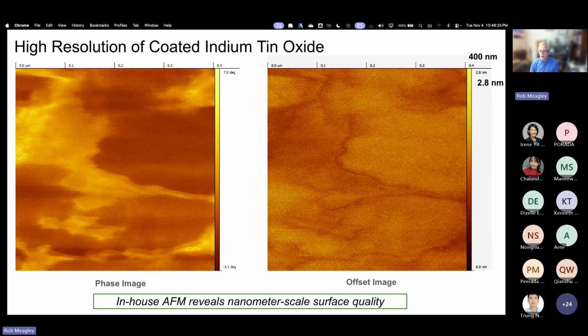And as Chen-Shu pointed out, the phase image can give you an understanding of differences in hardness that can relate to chemical composition. And, very clearly, even though in the topography, we see a step. This is actually a crystal grain merging into the next crystal grain over. But in the phase image, you can see that the crystal grain on the right looks somewhat different than the crystal grain on the left. And we believe that there is a compositional shift. What I really can't go into is the nature of the material that's sitting on the indium tin oxide, but I think you can see that at this resolution, there is definitely a real significant change in the nature of this film, and I believe we're looking at compositional variation across the surface.